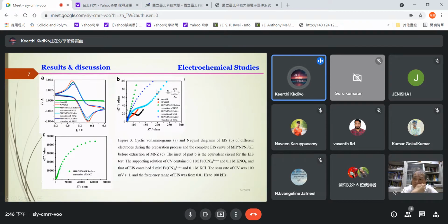Figure 3b shows the impedance result of the modified electrode. The semicircle at high frequency corresponds to the electron transfer resistance. It can be seen that a small semicircle was obtained, indicating a small interface resistance, and the electrode modified with nanoporous nickel showed no semicircle due to its high conductivity. When the molecularly imprinted polymer was electrodeposited, the impedance value increased due to the non-conducting nature of the molecularly imprinted polymer. However, after removing the metronidazole, the charge transfer resistance value decreased, showing the successful formation of pores due to the extraction of the metronidazole. At the last step, rebinding the metronidazole to the molecularly imprinted polymer on the nanoporous nickel GC electrode changed the impedance values, which could be due to the pores being occupied by metronidazole.